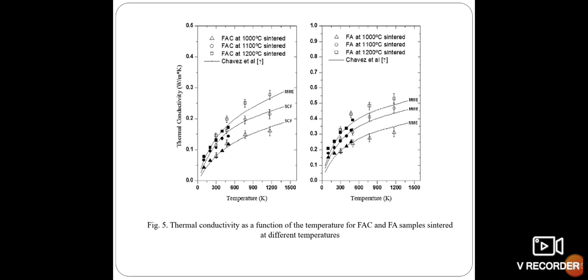For instance, the thermal conductivity of YSZ, yttria stabilized zirconia, as a function of grain size has been measured up to 500 Kelvin with values ranging from 1.2 watts per meter Kelvin to 2.3 watts per meter Kelvin. Therefore, the FAC and FA materials reported here present lower values of thermal conductivity at higher temperatures.